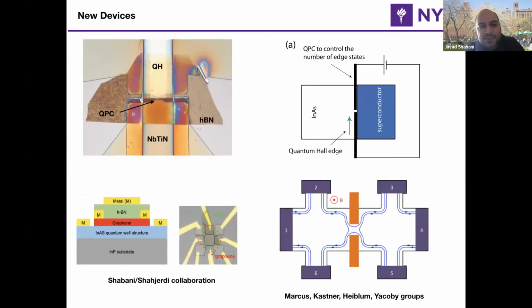So what is the future? I was hoping to actually show you data on our QPC sample. We make these Hall bars, on the top left, where you bring quantum Hall effect next to niobium titanium nitride. Now what I want to do is put a QPC exactly at that interface and look at the regime where I have a very small interface.